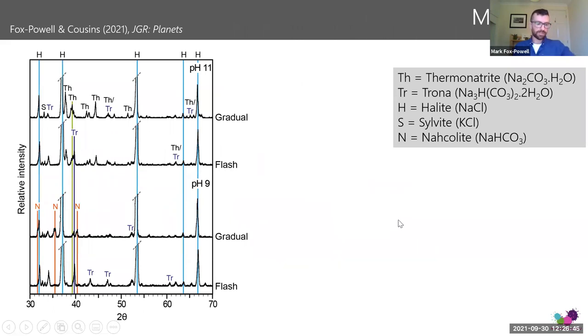We also looked at the bulk mineralogy of our experimental ice grains. And this is just an X-ray diffraction plot. What we're seeing here are these traces. We have all of our experimental conditions represented. We have at pH 11 the upper two traces, pH 9 the lower two traces, and both gradual and flash freezing experiments are represented on the plots.